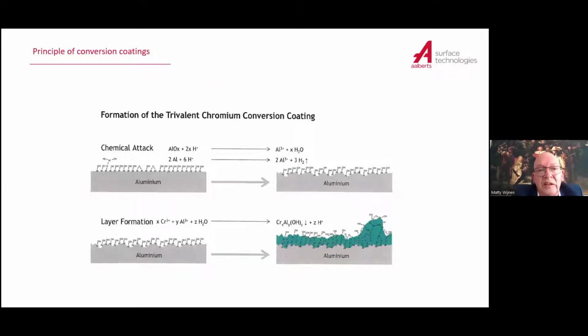Looking at the forming of those chromate layers, the chromate conversion coating, see here on this picture what happens. You have the aluminum. The aluminum is dissolved, as it is put in an acidic solution. The aluminum goes over into aluminum 3+. The aluminum 3+ connects with the chrome in the bath and forms a chrome aluminum coating layer which is on your product. It's a part of your product.